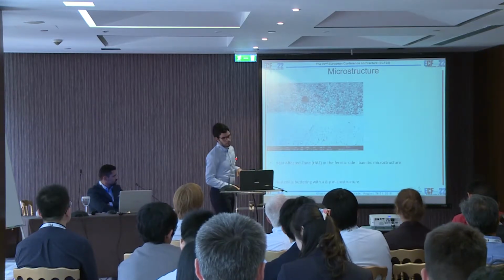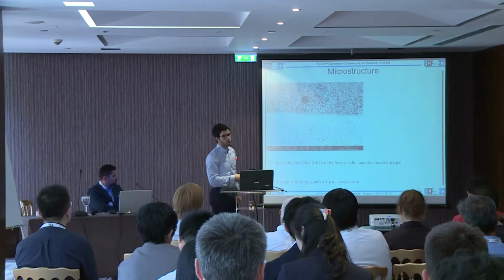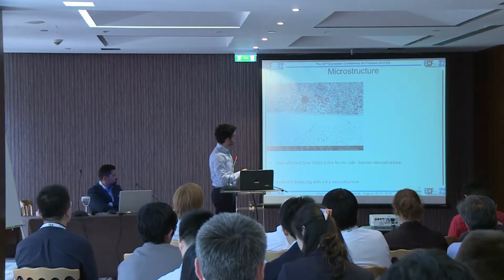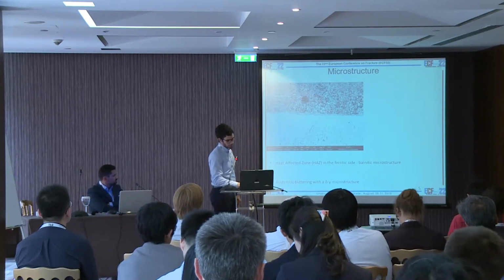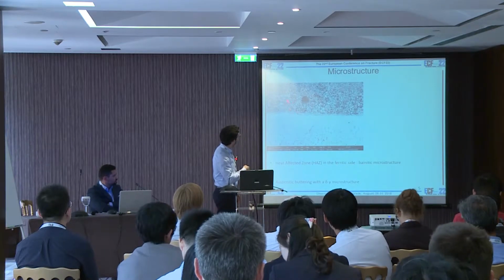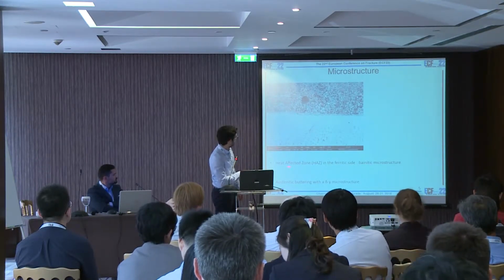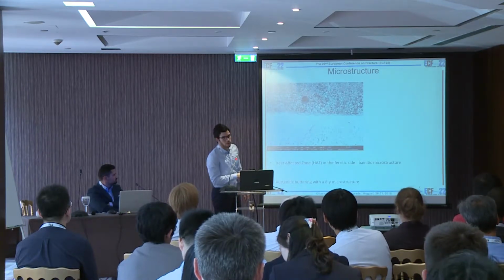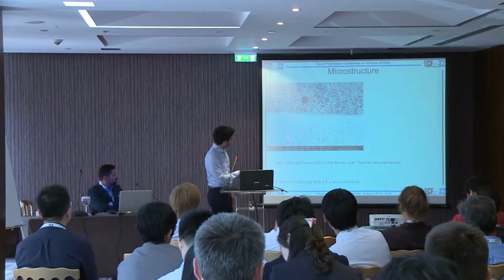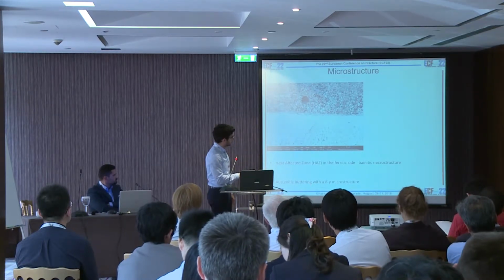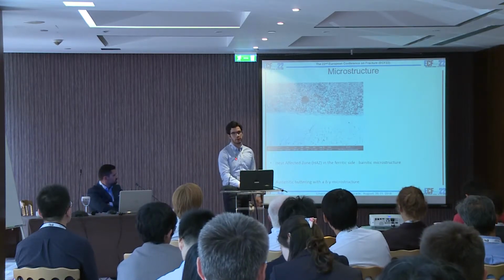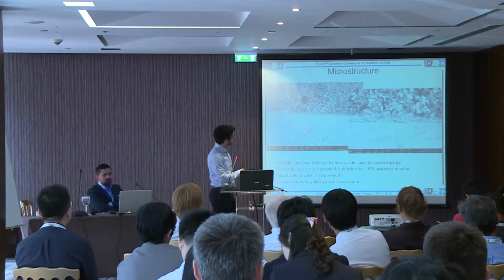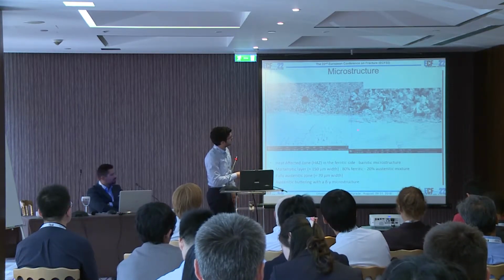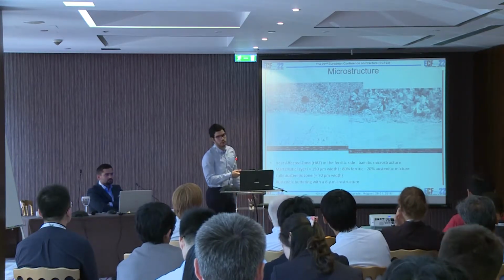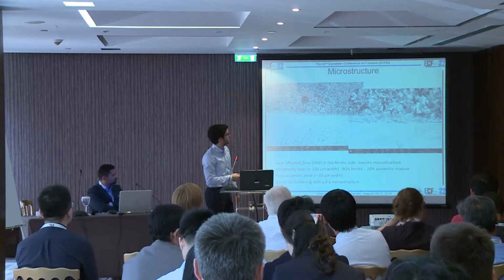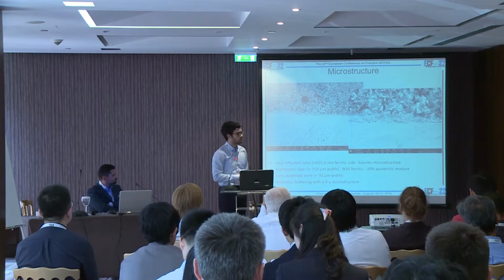Here you can see an image of a polished and etched specimen, and we can see the different microstructures across the ferritic buttering interface. On the ferritic side, we have the ferritic heat-affected zone, or HAZ, which is characterized by its bainitic microstructure. On the austenitic side, we have the austenitic buttering characterized by an austenitic microstructure with residual delta ferrite. Between the two, we have the interface, which is composed of a fully austenitic zone, without residual delta ferrite, which results from a primary austenitic solidification mechanism during welding.